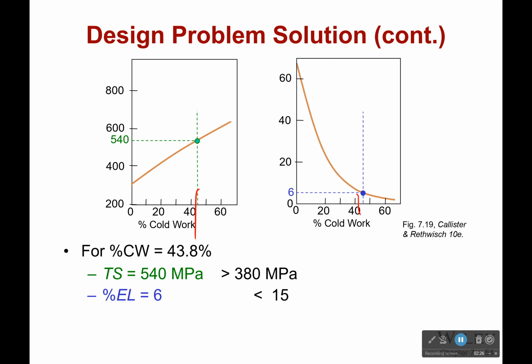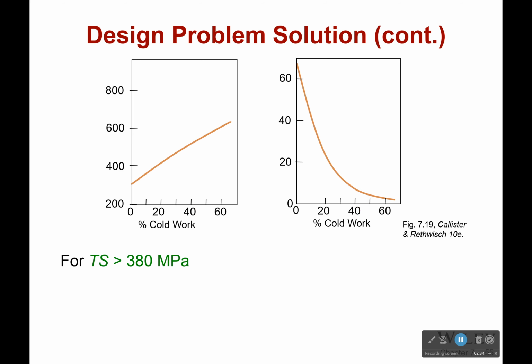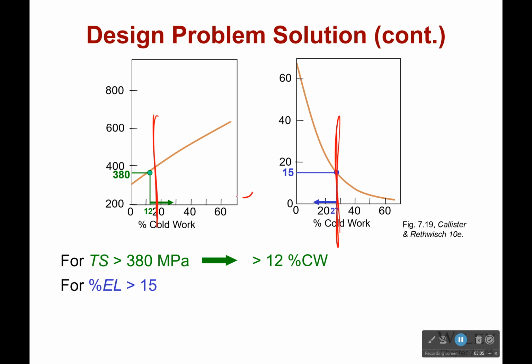Because of this, I'm going to have to heat treat my material until it has the right properties. For a tensile strength of exactly 380 megapascals, that would be about 12% cold work. For a percent elongation of 15, that would be 27% cold work. These are now our bounds for our cold working. If we're somewhere between 12 and 27, we will have both the tensile strength we need as well as the percent elongation we need. So somewhere in there is going to be our sweet spot.